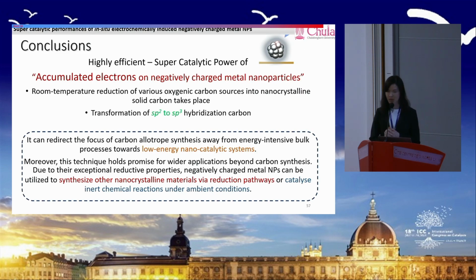So in conclusion, I believe I showed you this. There exists a highly efficient supercatalytic power of this negatively charged metal nanoparticle with accumulated electrons on it that can do this reaction and even the sp2, sp3 transformation. So in a broader context, we believe that this synthesis could shift from energy-intensive bulk processes towards low-energy nanocatalytic systems for carbon allotrope synthesis. It's possible to apply this to the synthesis of other nanocrystalline materials as well, or maybe even catalyze any inert chemical reactions under ambient conditions. There's a lot of possibility here.